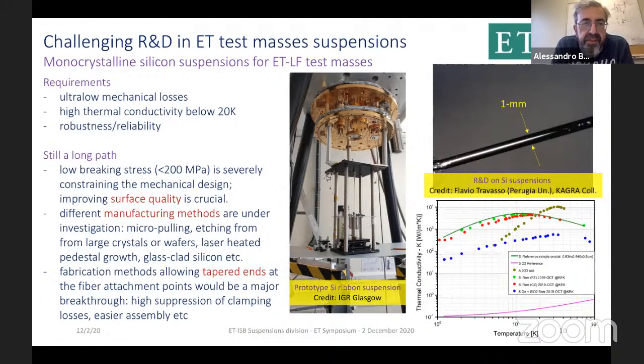The main one is for the low frequency detector. The baseline design foresees silicon suspensions, monocrystalline. So the requirements are very aggressive. We need to combine ultra low mechanical losses. We want to have high thermal conductivity below 20 Kelvin. And this suspension should be reliable, so it should be robust as well. The path is still very long.